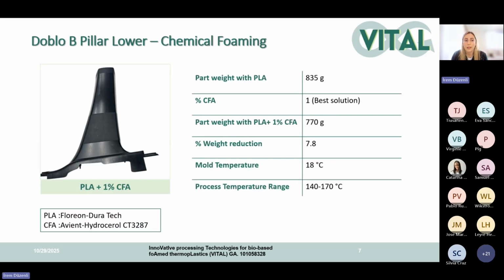Now I want to give some examples of our use cases in the Vital project. This is our latest result from the project. We can say that we achieved nearly 8% weight reduction, and we are now using 1% chemical foaming agent in our process. During our trials, we tried a lot of things. We tried process optimization, and we always changed the chemical foaming agent amount to get the best optimum parts. And we use a cold mold in this process.